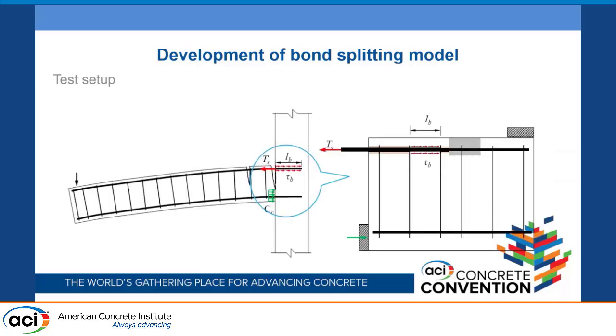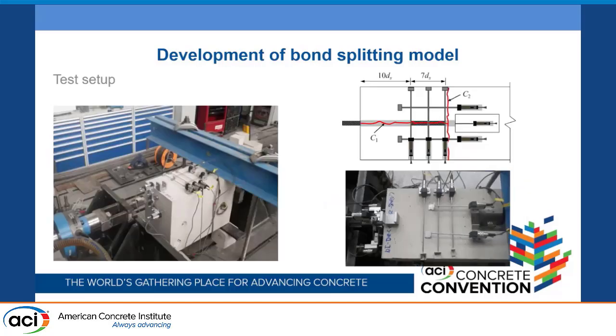Further, for the test setup, we said, okay, what happens in reality? So if you have a column to foundation or a beam to column kind of connection, then if you have a rebar here and it is being pulled, then we have, let's say, a critical crack here, and then we have the bar which is subjected to the bond stresses. So that we took over and converted into, okay, the equivalent would be the beam end specimen, which is already the concept of the beam end specimen given in ASTM also. However, we consider the transverse reinforcement in a different way compared to how it is used in the beam in the ASTM specimen. That shows the typical test setup.